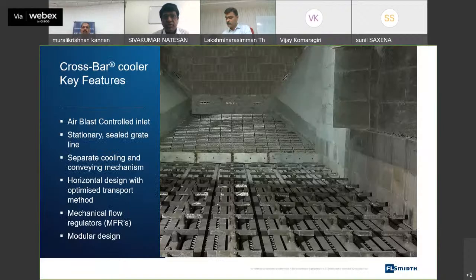Then in the crossbar cooler, we know that the special features are, as we just saw, that it is air blast controlled, and it has a stationary sealed grate line, a separate cooling and conveying mechanism, and mechanical flow regulators. The particular point is the separate cooling and conveying mechanism, where the conveying is done by the crossbars and the plates are always stationary. So the performance of the cooler remains the same even after startup and a few months of operation. Even before shutdown, if we take the efficiency parameter of the cooler, it remains intact.